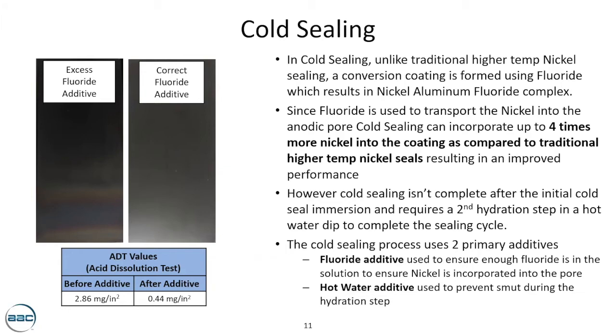So we're not filling it with nickel like we were in the other steps, we're filling it with a nickel aluminum fluoride complex. And by doing so, and by using fluoride as the vehicle to incorporate nickel, not just a concentration gradient, we're able to get 4 times more nickel into the coating compared to traditional high temp and mid temp nickel seals. So what that means is the battle that you're fighting between hydration and nickel incorporation